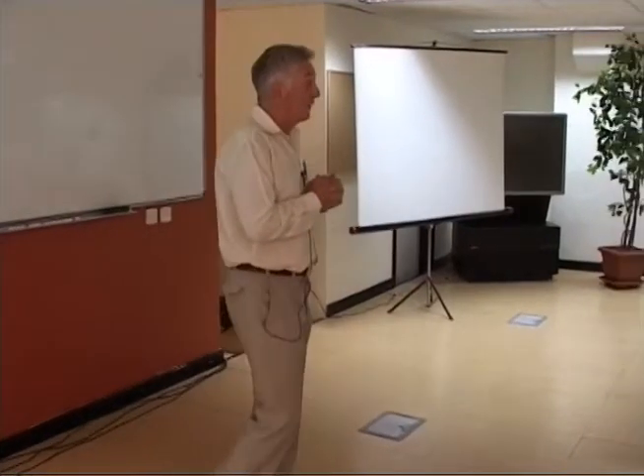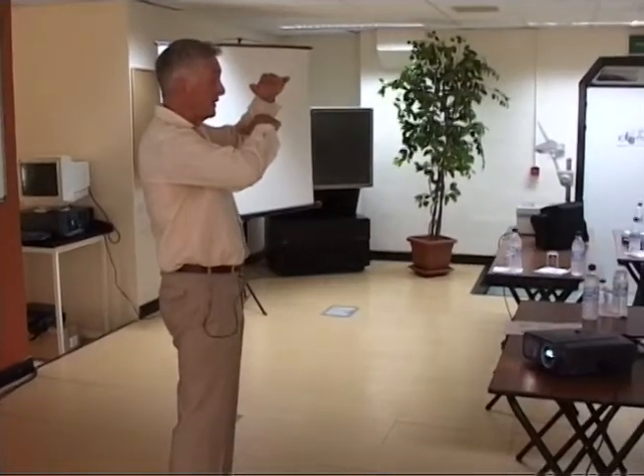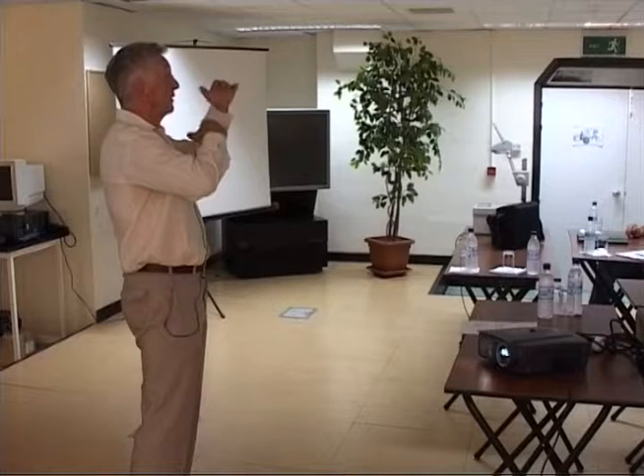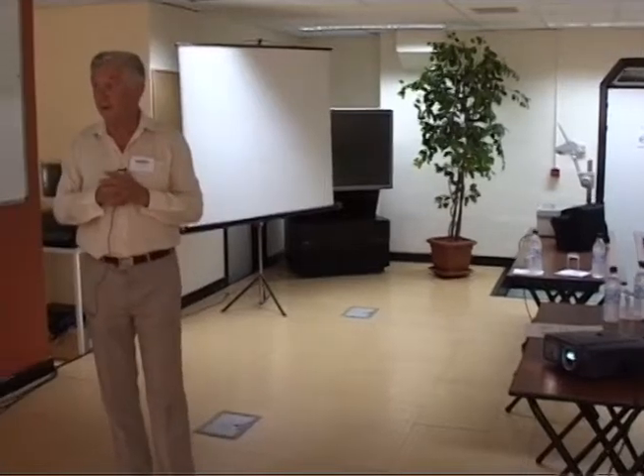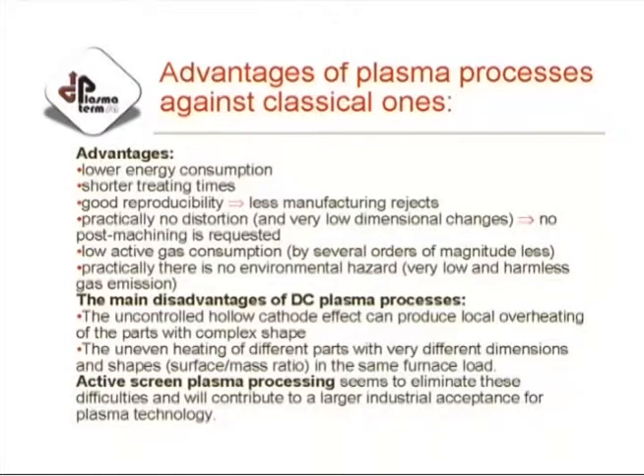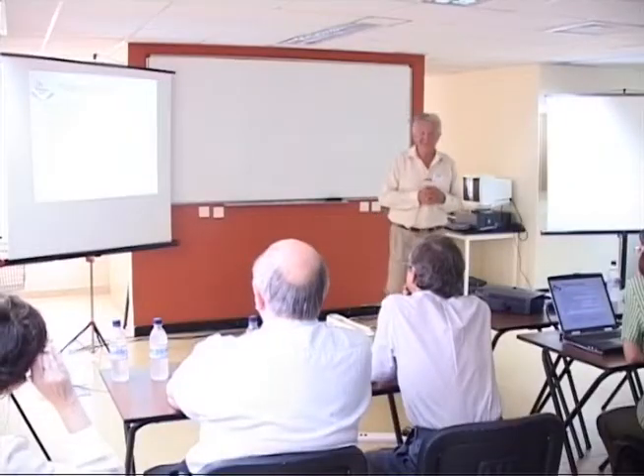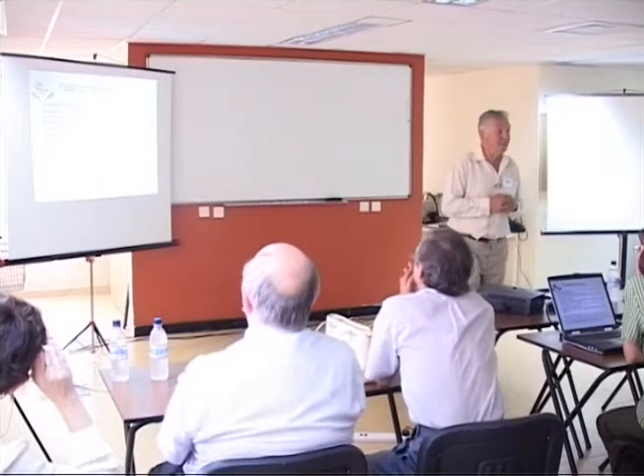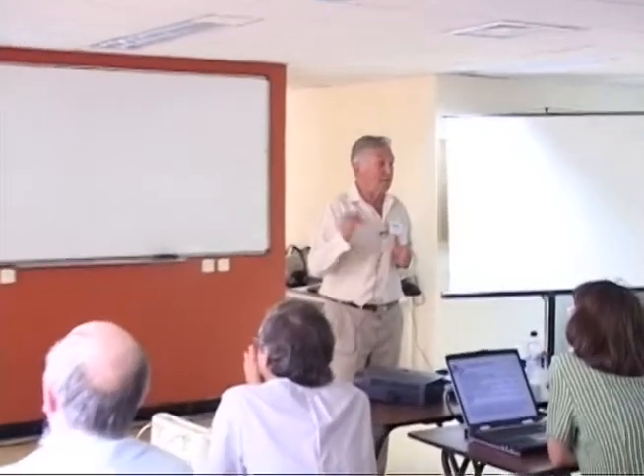So the main disadvantage of this kind of DC plasma process is that the uncontrolled hollow cathode effect may produce local overheating. And we had this problem at the beginning with the shafts. Between the two surfaces, due to this effect, we had an overheating, and the results were not always uniform. Certainly, uneven heating of different parts could appear when you try to put different parts in the same load in the furnace, which caused also problems. This probably will be solved by active screen treatment, which is a new procedure and probably heard about in the lecture of Professor Bell.